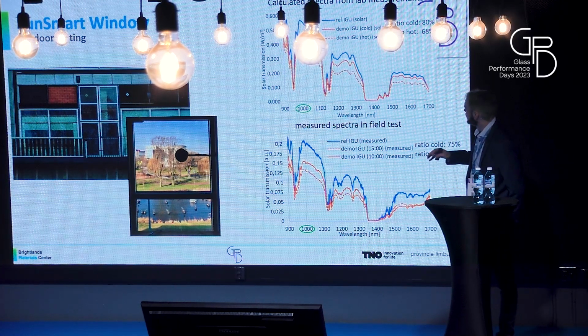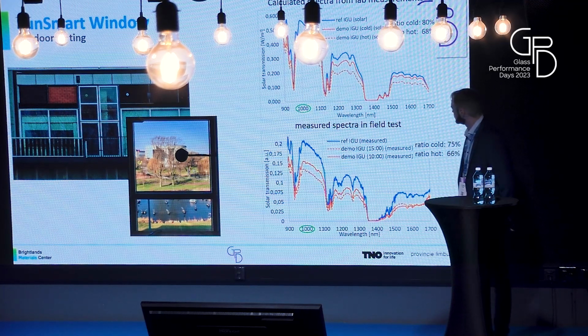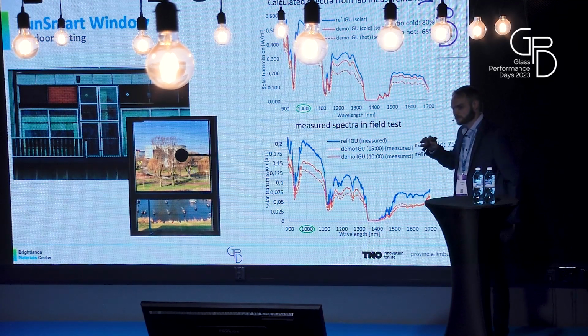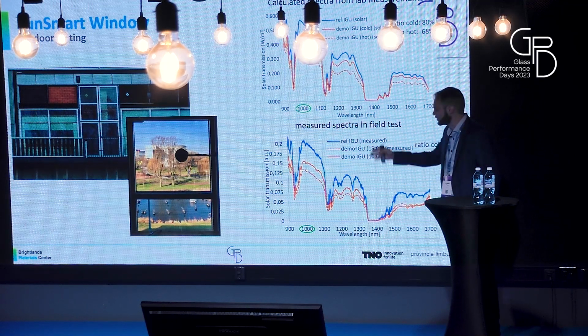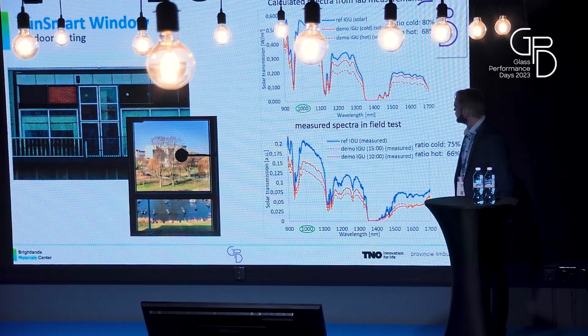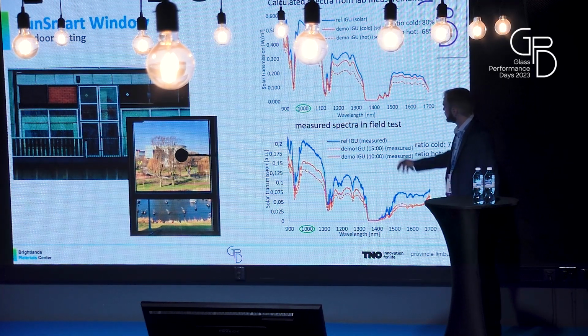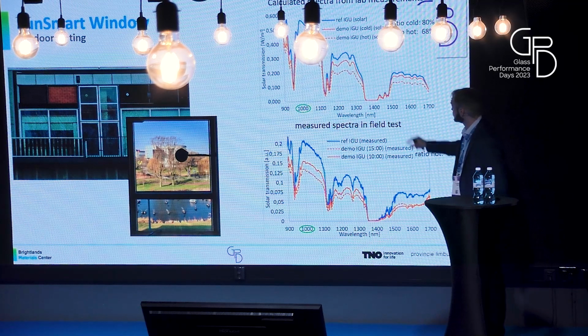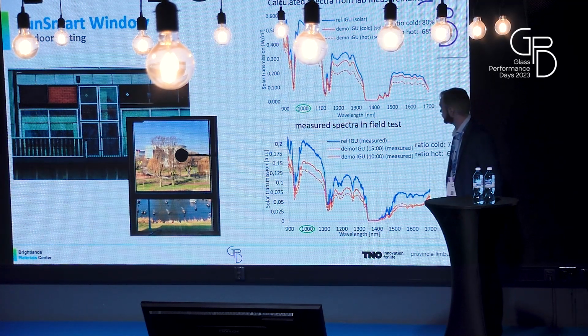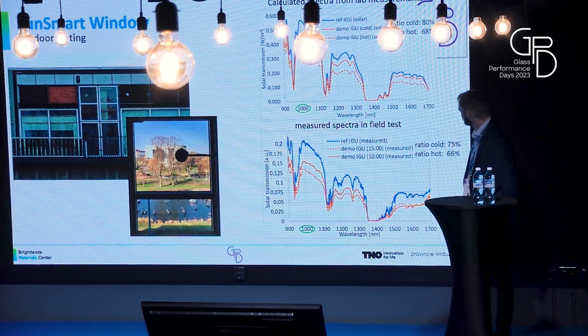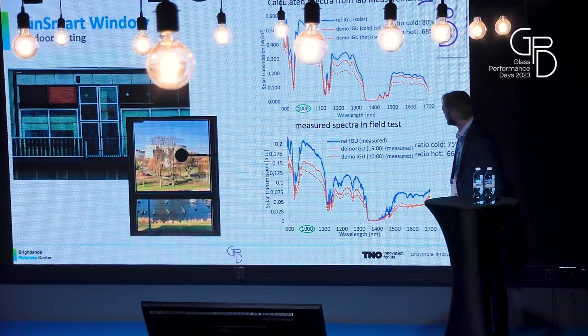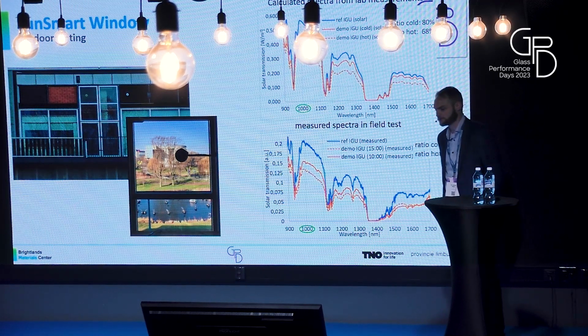The first thing that we looked at was, does the material perform as we want it to perform? And there we did some calculations from optical measurements of all the materials that we used in the IGU, and calculated that together with the solar AM 1.5 spectrum to get an impression of what the transmission of our demonstrator IGU, in comparison to a reference without the thermochromic material, would look like. And then we compared it to the measurements which we did in our demonstrator. And we were very happy with that because the obtained spectra matched very well with the expected, and the performance was very similar to what we expected from our lab results.